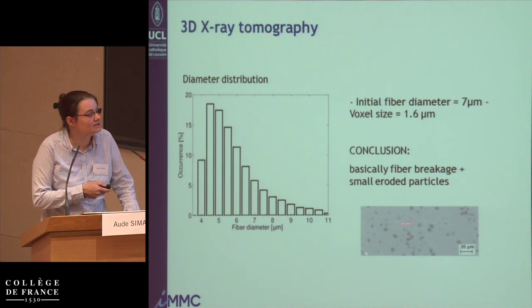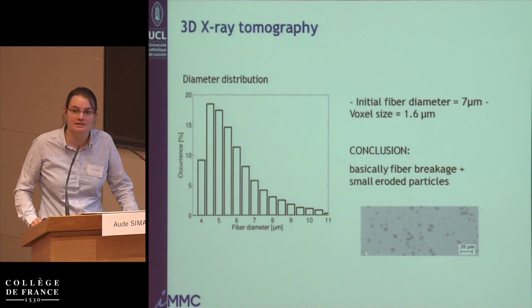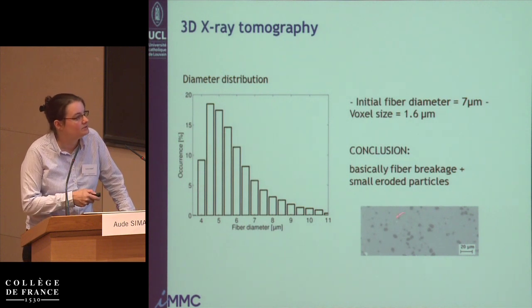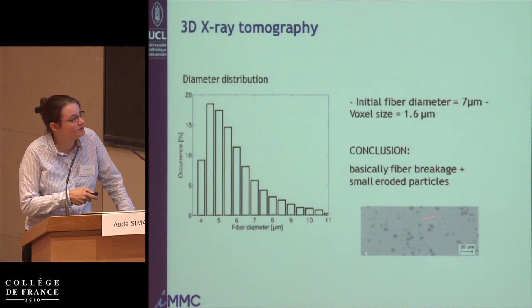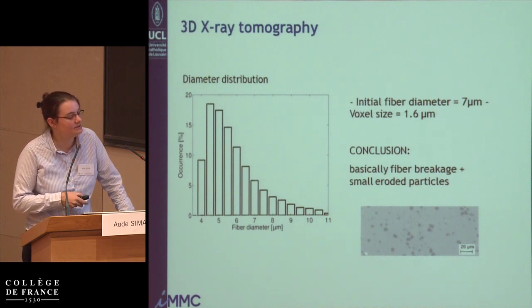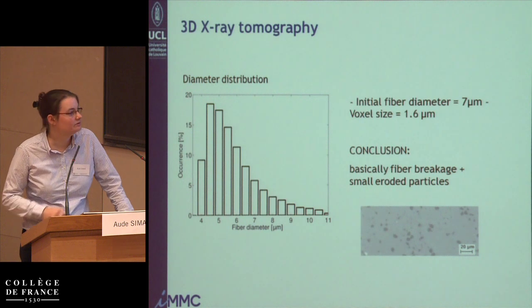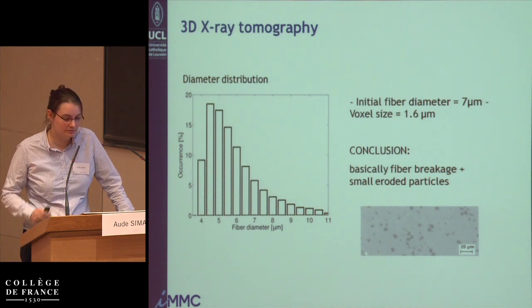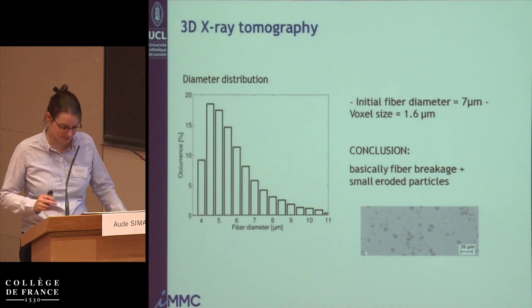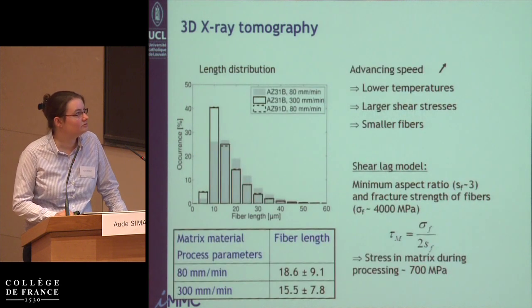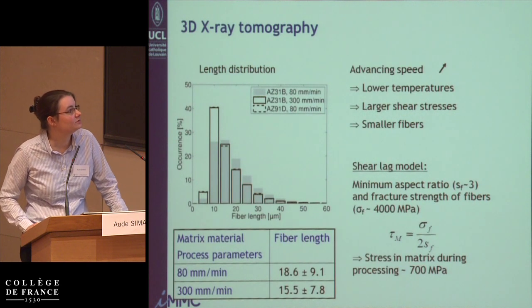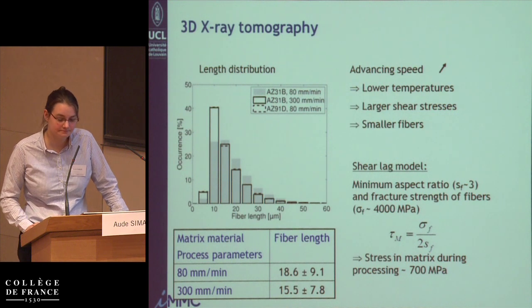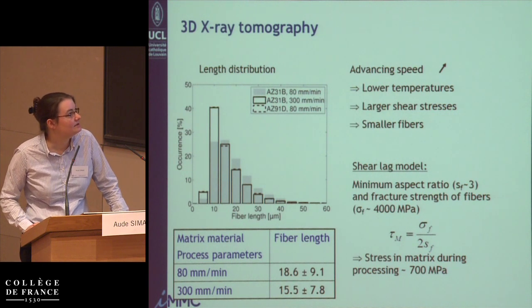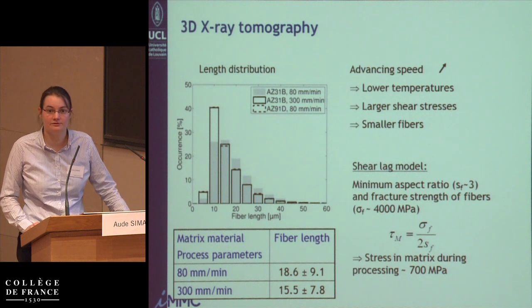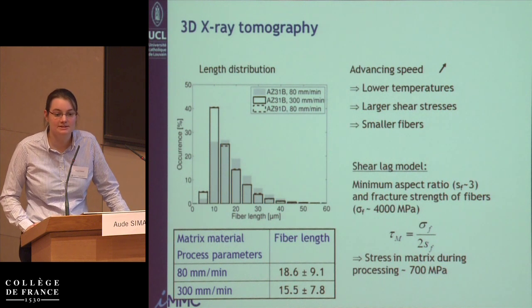The erosion that you can see here on this scanning electron microscope image, well, you see here that you have a couple of parts that have been eroded from the larger fibers. But basically, you're remaining with larger fibers. Now, the main interesting question is, of course, what is the length of these particles, and that will affect their ability to reinforce the material.